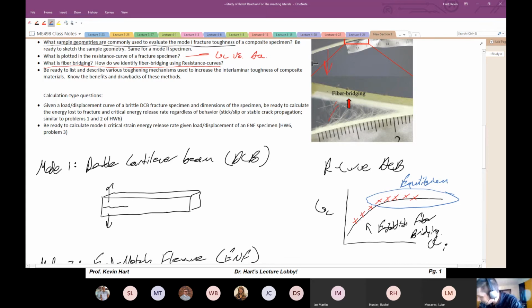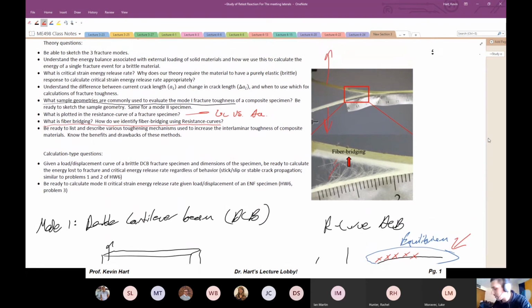All right, so there are fibers over here on the left hand side that are being ruptured as the crack is propagating, and obviously we're forming new bridges on the front end here as the crack propagates. Until there is an equilibrium between how many we are losing on the left hand side and how many are reforming on the right hand side, we're not going to reach a plateau. But once it does occur, then you see this equilibrium in the R curve. All right, so that's how we identify fiber bridging, and that's what fiber bridging is. It's fibers across the interface which help toughen the interface there.